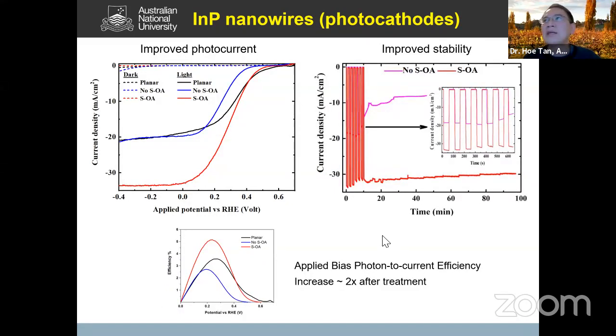And when we do the photoelectrochemical experiment, you can see here the photocurrent. Now this is negative because this is a photocathode. You can see now with the sulfur oleylamine treatment, the photocurrent is significantly enhanced compared to the one without the treatment. Okay. And if you look also at the lifetime, after the sulfur oleylamine treatment it is significantly longer than the one without, not treated. So not only is sulfur oleylamine able to remove the damage, but it also passivates the surface so that it enhances the lifetime of the photoelectrode.